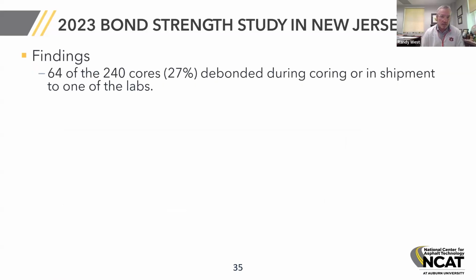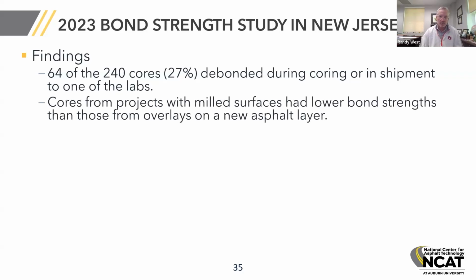First of all, we saw that 64 of the 240 cores, about 27%, debonded during coring or during shipment to the labs. And they took care to make sure that the cores were well protected, put them in concrete cylinder molds before they sent them to us. And so they weren't mishandled.